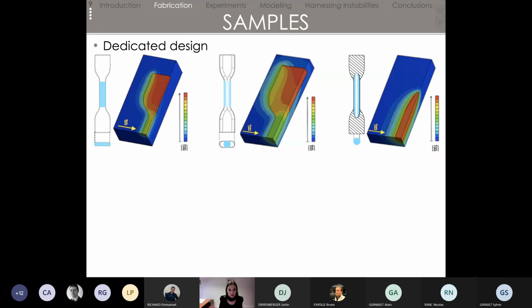So when we're doing mechanical testing, we want to have uniform quantities in the gauge area. So that's why we started with the first sample here on the left, which is a classical dog bone sample with a rectangular cross section. If we are simulating this sample under magnetic field, you may see in the middle that we have yellow and green, which means it's not uniform in terms of magnetic field in the gauge area of the sample because of the corners. So with these samples, we cannot really envision doing material characterization.